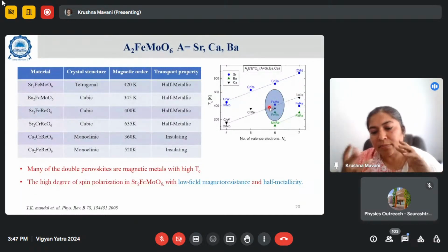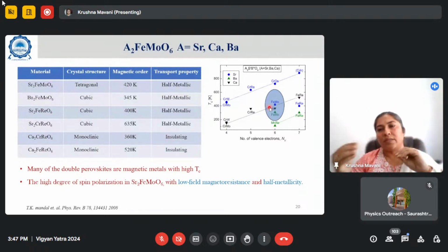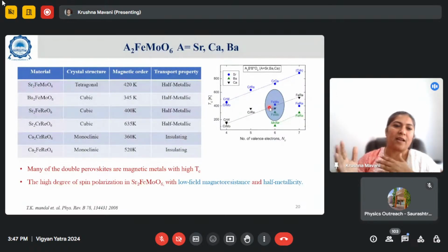It is a flexible perovskite structure. You see, it can accommodate a variety of 3D metal ions. That is more interesting. So the degrees of freedom at the lattice level are quite high, and without losing its phase diagram, it can change the transition temperature slightly here and there. So you can harvest this situation for the benefit of your requirement, right?